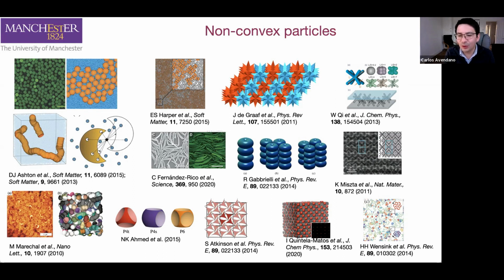The first step, obviously, is you always need the phase diagram, because when you try to study nucleation, you need to make sure that your system is in supersaturation. And depending on the degree of supersaturation, you can have different energy barriers. So the first step is always to calculate the phase diagrams, and then to move into the experiments on nucleation. Now, something I didn't explain because I had to go quickly, and apologies for that. Modeling convex objects in Monte Carlo is relatively simple. You just need an overlap detection algorithm, and that's all you need.